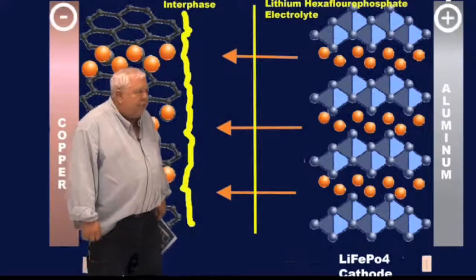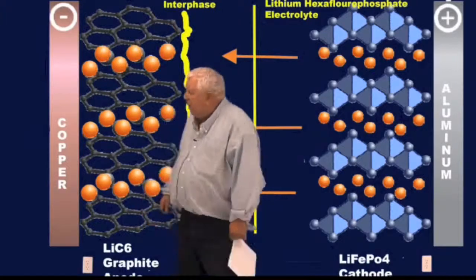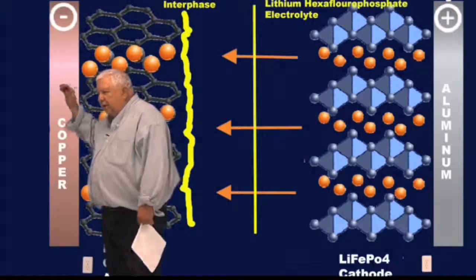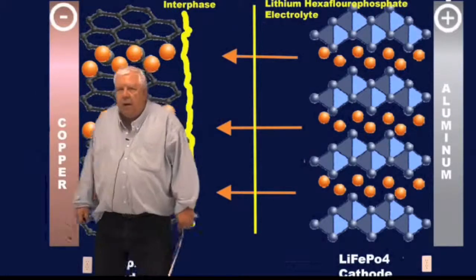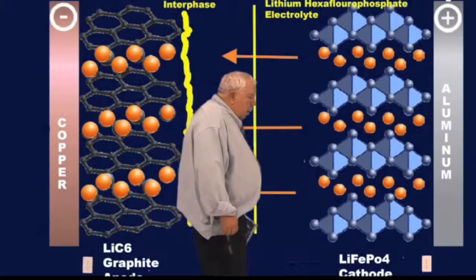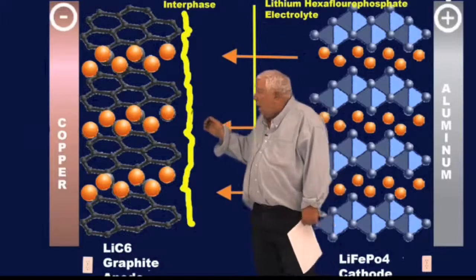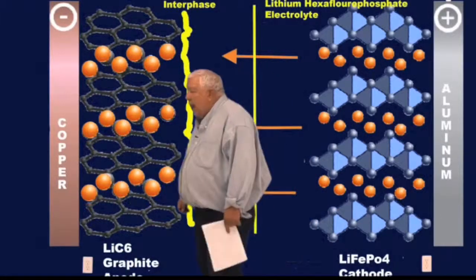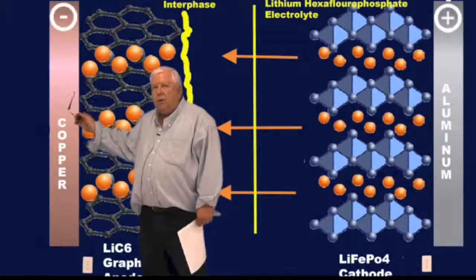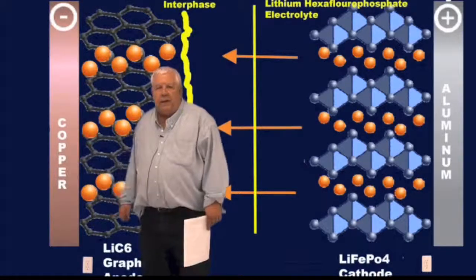And so the lithium plates onto the graphite. And as that builds up, it reacts with the SEI layer, with the solvents. And so we have this massive scab growing on our anode and diminishing our capacity. But if we do it enough where we short this cell, it will go into thermal runaway and you'll have quite a fire. And it feeds on itself. As it goes into runaway, it gets hotter, the SEI layer melts, and this thing takes off.